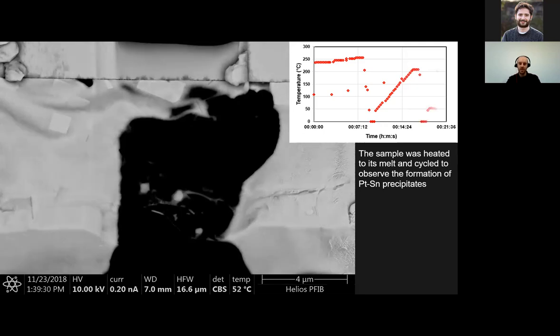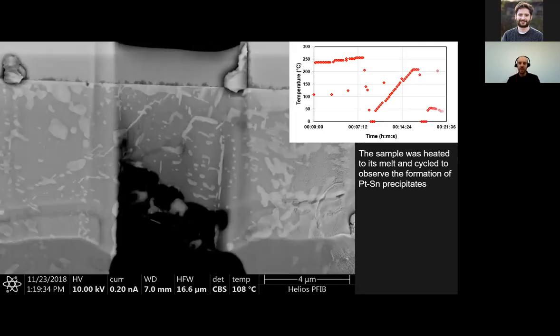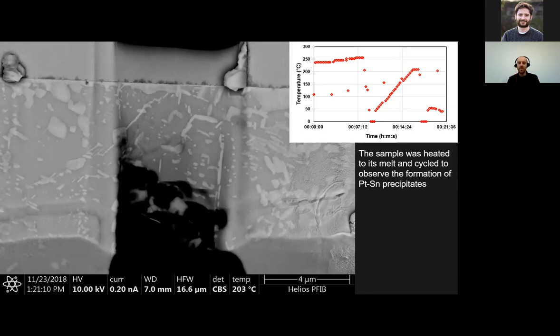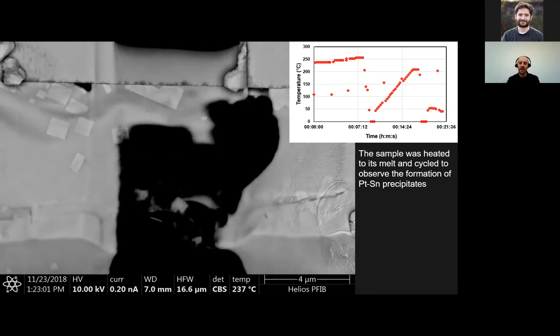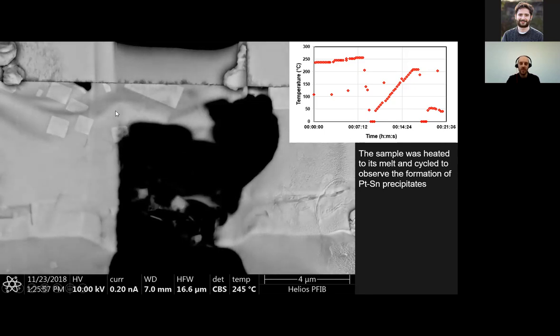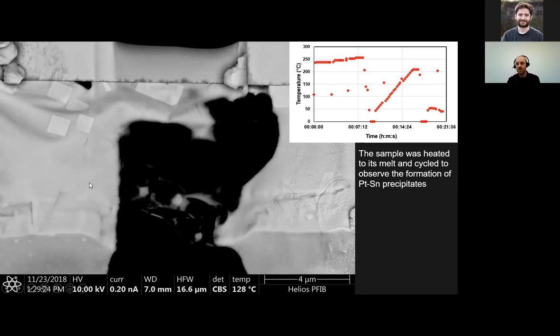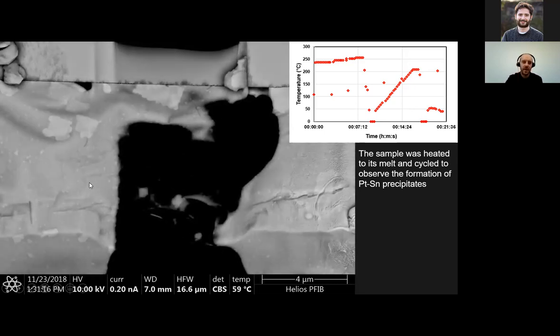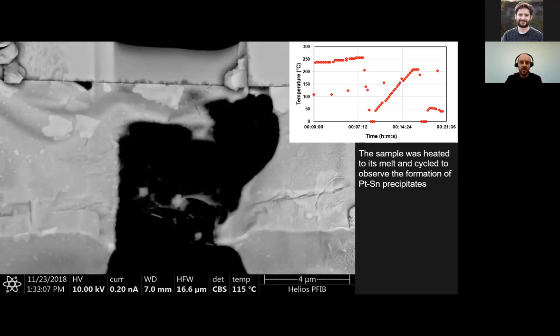A few other people have commented on this, but this allows us to melt the tin, solidify it and remelt it again and again, and look at the different precipitates forming. By changing the cooling and heating rate, we could form different precipitate shapes, which was quite fun and gave us some ideas for future research that we could do.